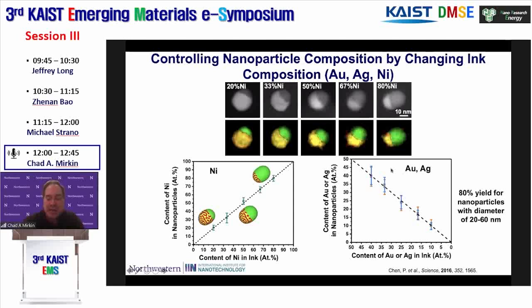One of the other things is, you can actually monitor the birth and growth of a reaction under an electron microscope. You can cool down and watch the nucleation and growth process and tease out the whole trajectory of particle formation. What you see is every atom in that reactor ends up in the particle. This is another way of showing that.